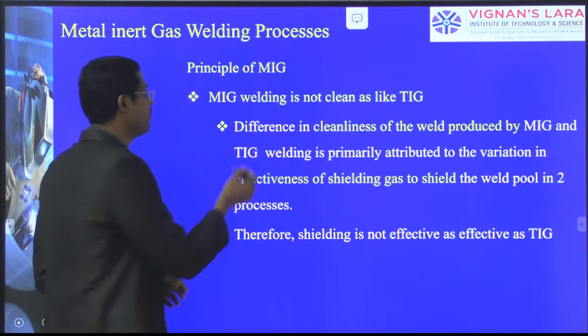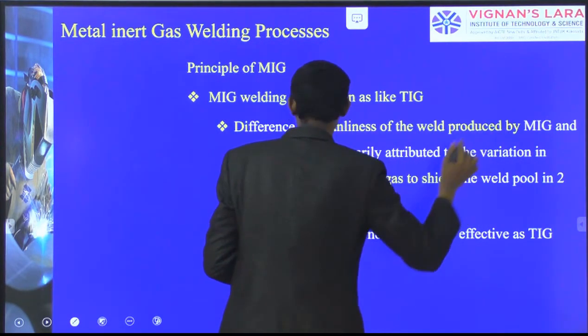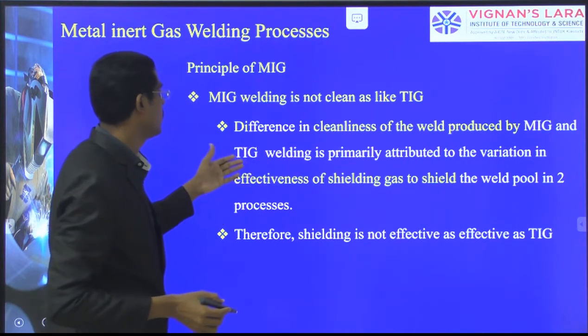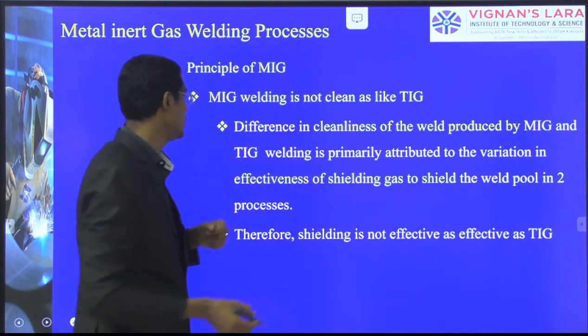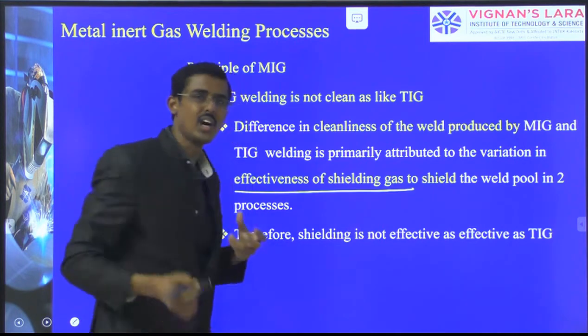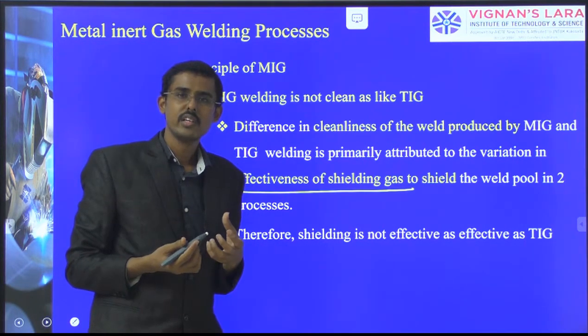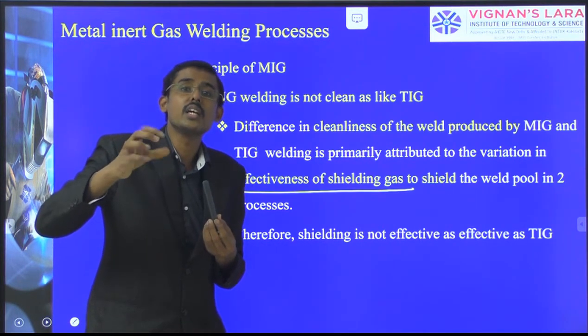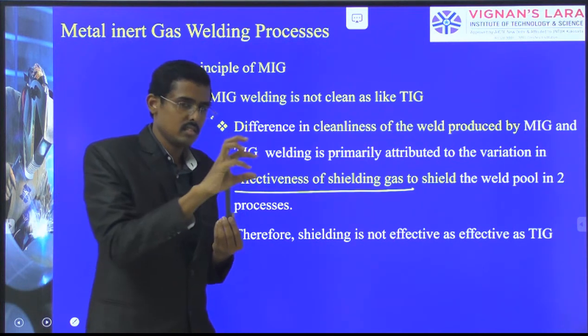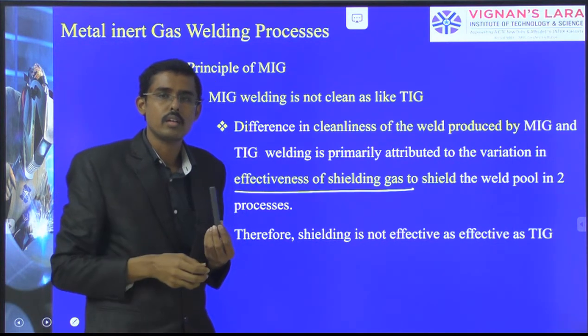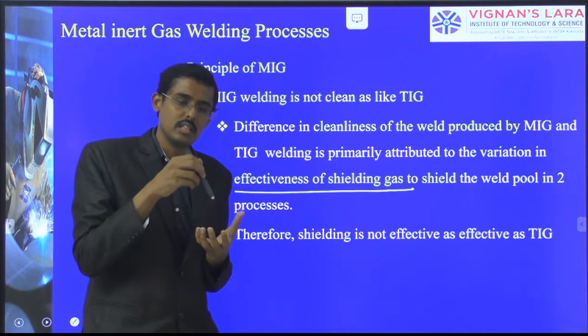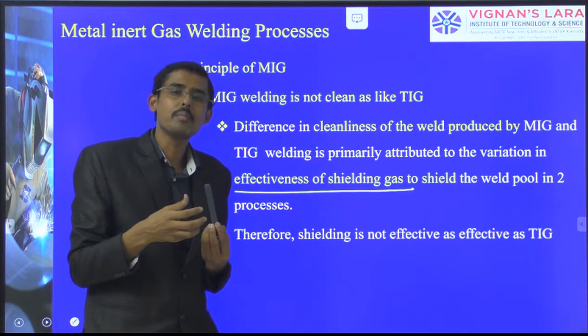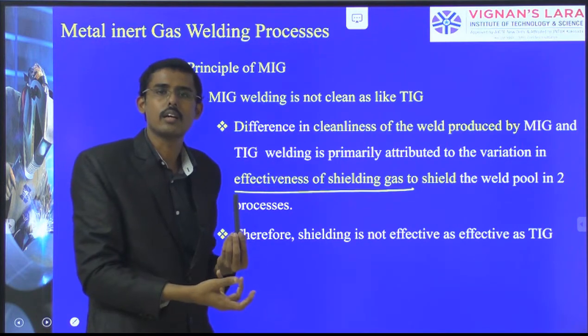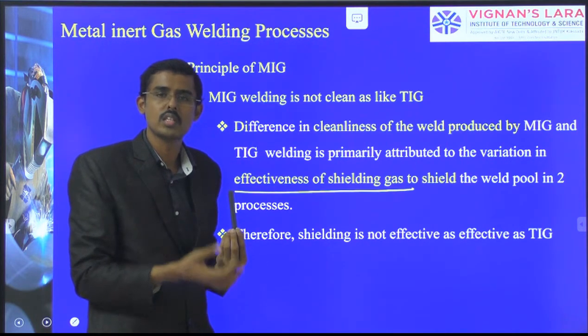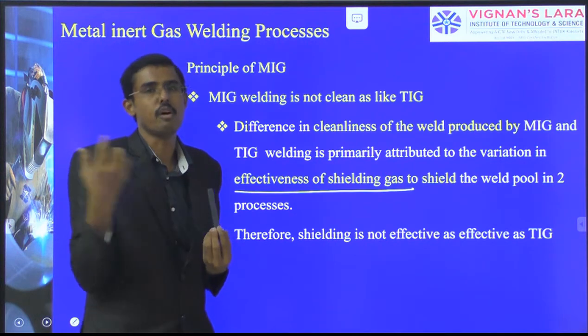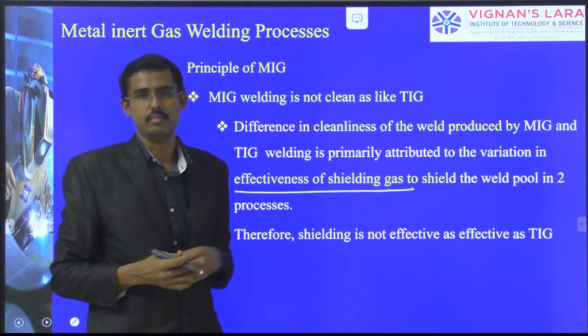Principle again. The differences in cleanliness of the weld produced by MIG welding and TIG welding are primarily attributed to the variations in the effectiveness of the shielding gas. How? If the shielding is not sufficiently given, the cylinder is not opened properly, then shielding is not supplied in sufficient amount. Then what happens? Shielding is not proper, which means automatically contamination, hydrogen embrittlement, porosities, defects will form. So sufficiently we should provide.